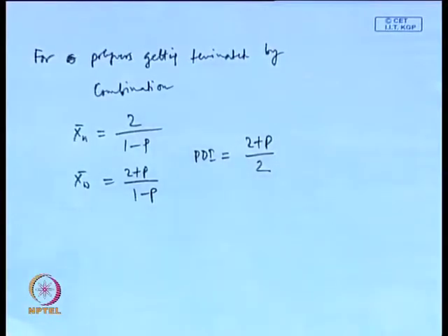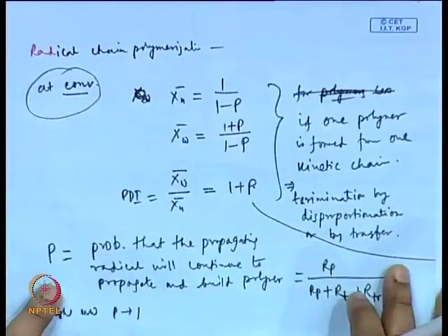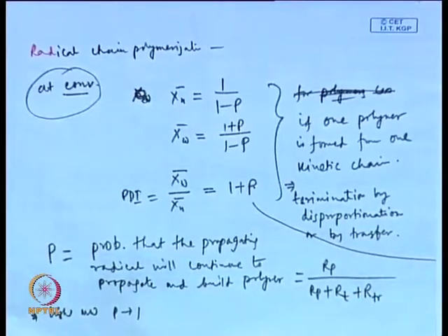Okay, so remember this is at low conversion, we are talking about the reaction that has just started, the reaction has not progressed too much. So, the concentration of monomer and the concentration of initiator have not changed much. So, the ratio of monomer by I to the power half has not changed much at low conversion.